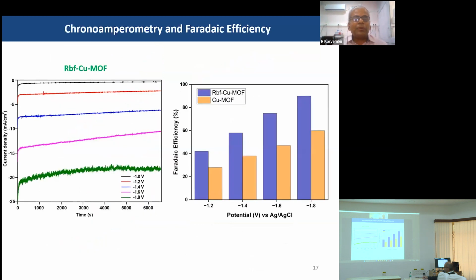From the chronoamperometric analysis, we can see that at -1.8 volt we observed higher current density, and we ran this chronoamperometry for 2 hours, which also gives the stability of the system.